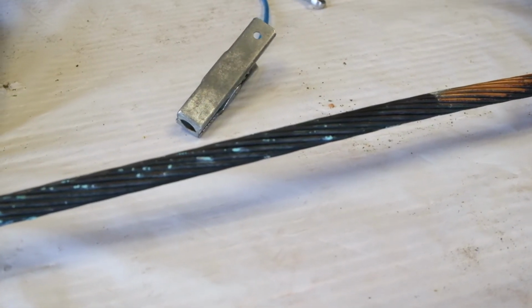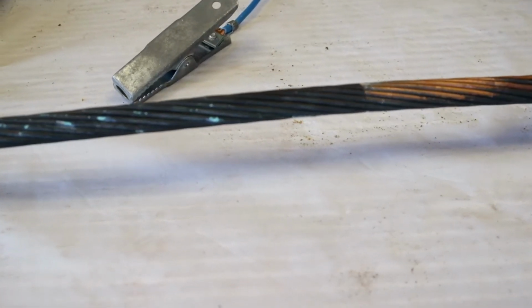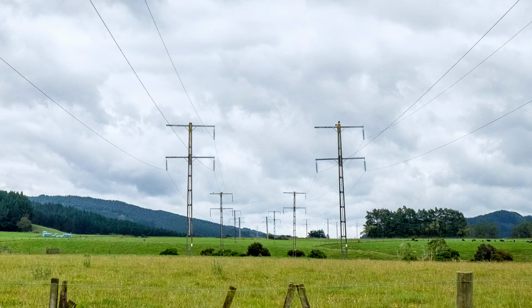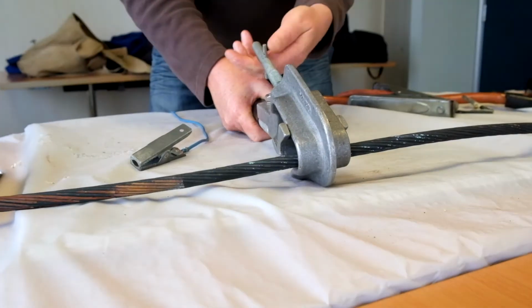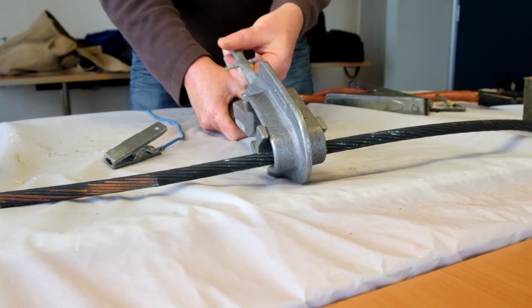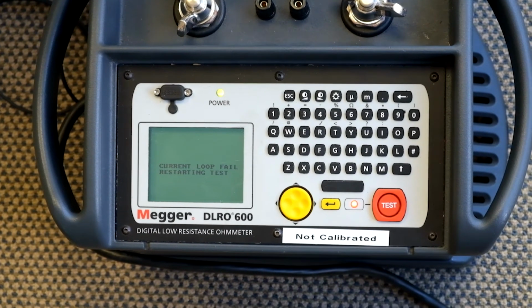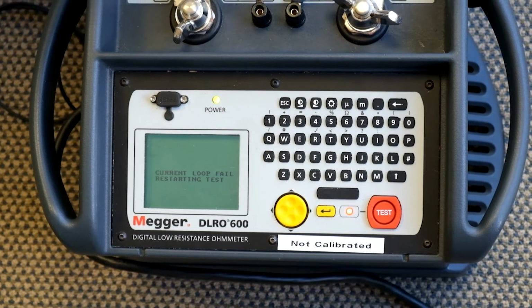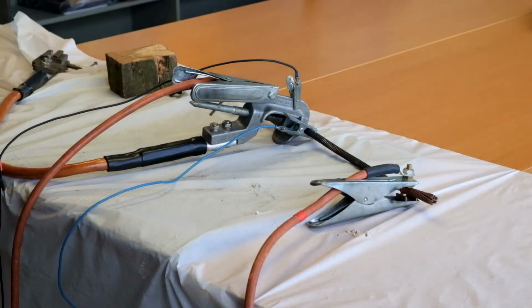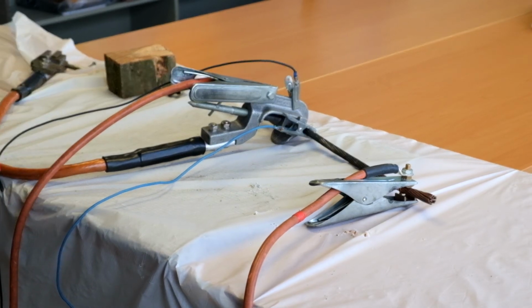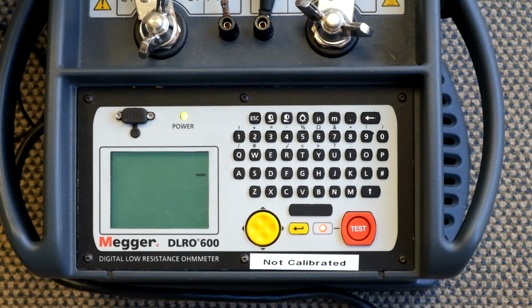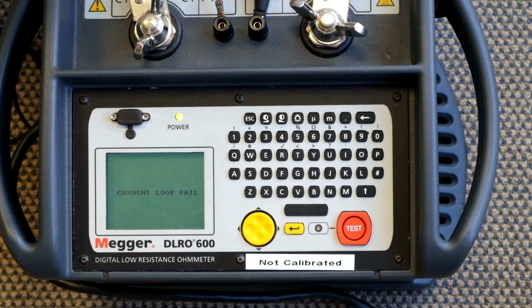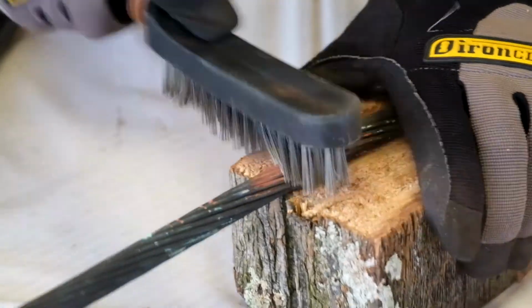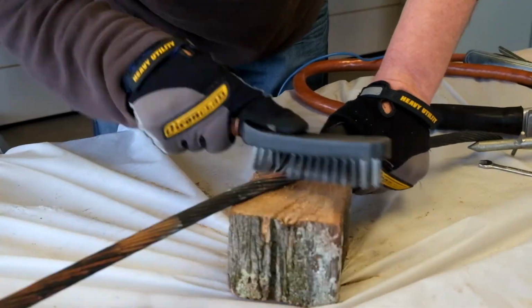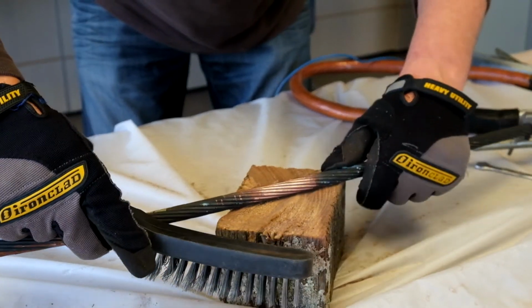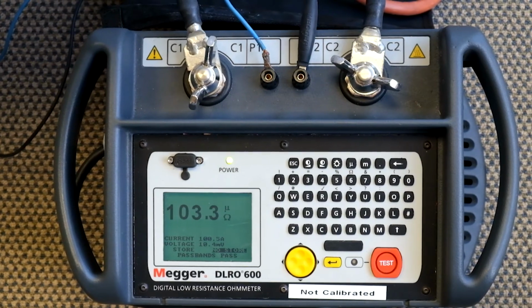We've got an example of a very heavily oxidized piece of copper conductor, similar to what was found on the recently dismantled Mangahao Paikakariki lines. Our first test doesn't return a result. The ohm meter shows the message, "Current loop fail, restart testing," which means the conductor is too corroded to get a reading. If you applied temporary earths to a conductor in this state, they simply wouldn't work as a means of protecting you from hazardous voltages. After some cleaning, we finally get a result of 910 microohms. After extensive cleaning, we get a satisfactory result of 103.3 microohms.